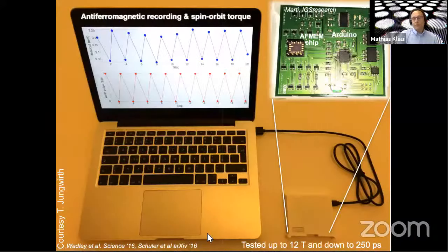Okay, and now we have the writing and the reading, and you can make a real device. So this is a slide from Thomas Jungwirth, who actually made such a device here, wire bonded onto a chip, which you can plug into your USB port. And then you have your 1-bit antiferromagnetic memory. Not very impressive, but what is impressive is that it works up to 12 Tesla and down to 250 picoseconds. So this really is a device that cannot be disturbed by the fields you can easily generate.